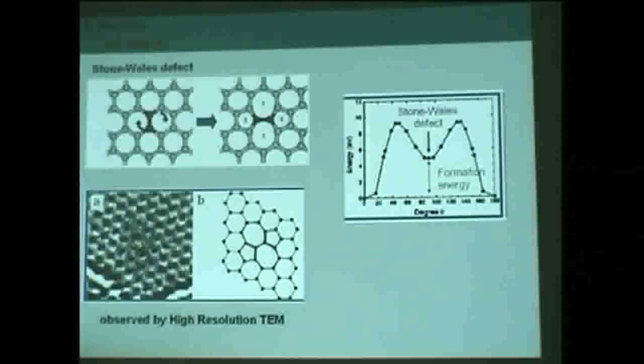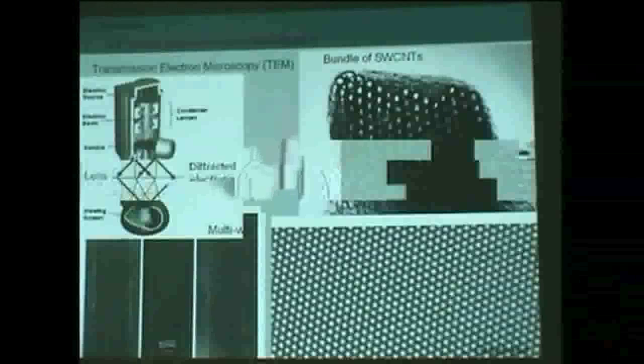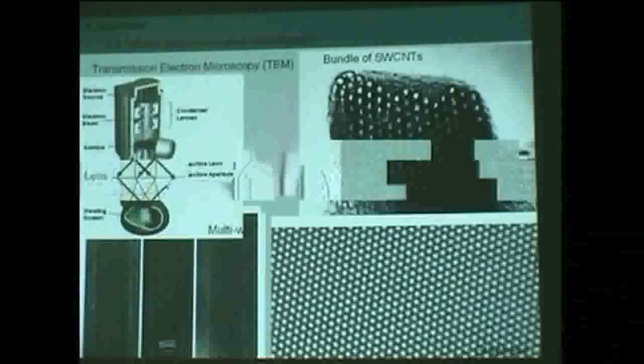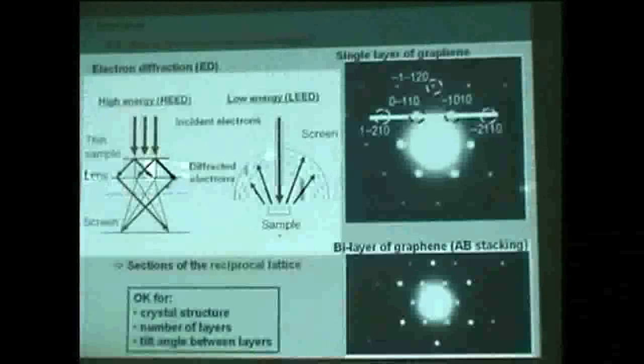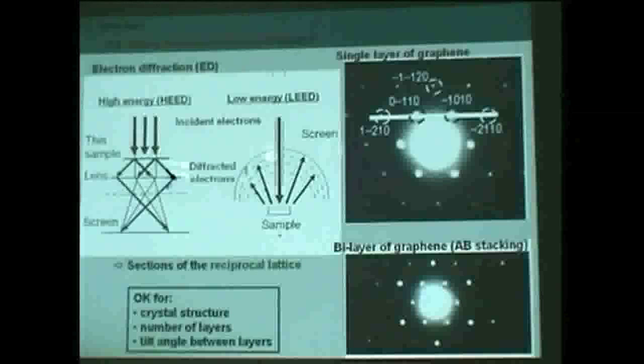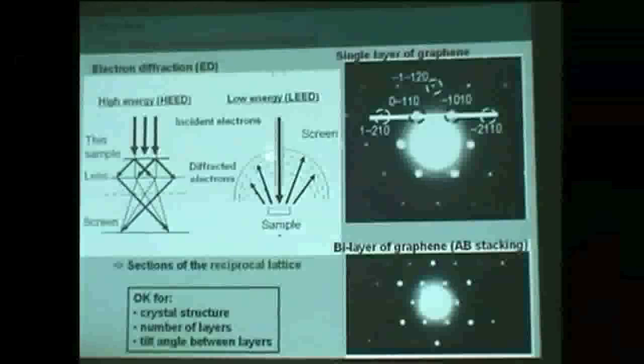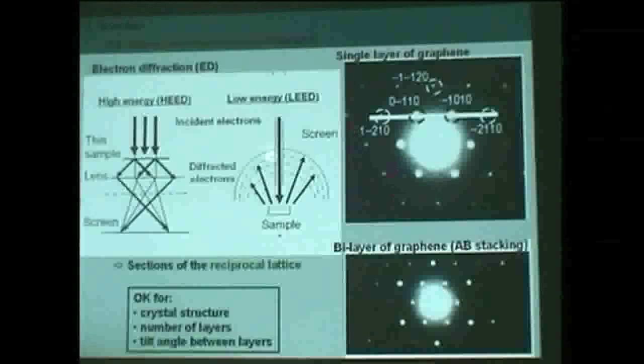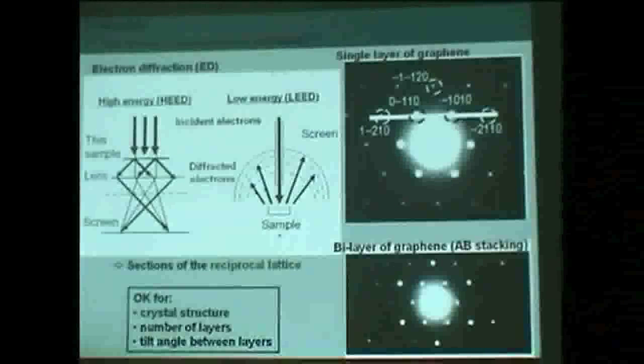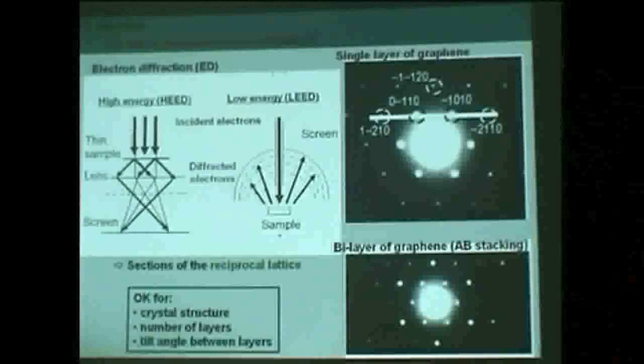One is easy, because it's already written: TEM. With TEM we get an image of the sample, and if one atom is missing, or if there is something added or something which is not symmetric, we can see it. What about electron diffraction? Can we know about defects? Not too much, especially if there is a low amount of defects - they will just be averaged out in the diffraction pattern. If we have something very disordered, very amorphous, then it will completely modify the diffraction pattern. But here we're talking about just a small amount of localized defects, so diffraction is not adapted to do that.